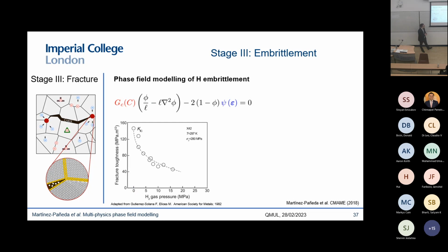And one way that you could do it is in a phenomenological way. So you could run experiments and measure fracture toughness versus hydrogen concentration and implement this function for that specific material. And this is one of the ways that some of our industrial partners decide to go ahead. However, I didn't like to propose a model that requires so much experimental calibration. Ideally, I wanted to propose a mechanistic model that had no fitting parameters whatsoever. And so I'll tell you a little bit of how I came up with what I think is the ideal fracture energy degradation function in the presence of hydrogen.